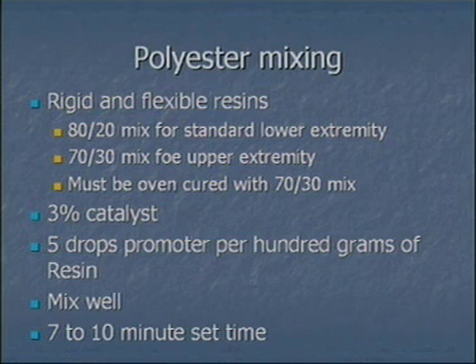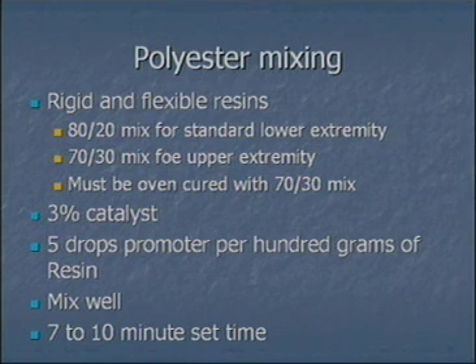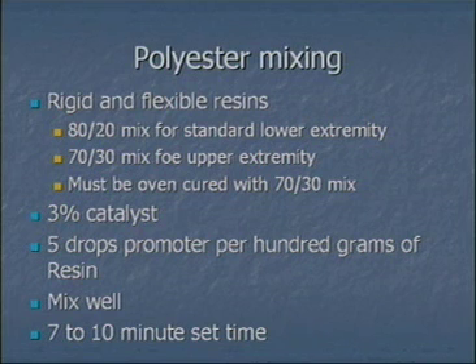So what you have to do is you have to cure it in the oven to force it to complete its cure time. And when you do that, then it hardens up and it's safe for the patient to use, but you must cure anything over a 70-30 mix. The catalyst is usually 3%, so 3% is your standard mix. So if you have 100 grams of resin, you're going to put in 3 grams of catalyst.